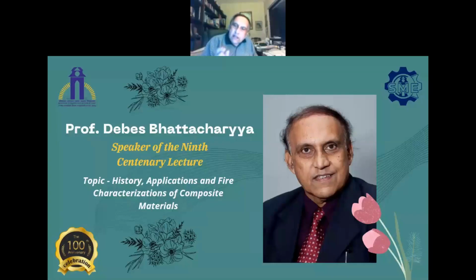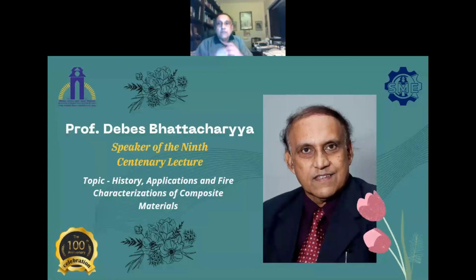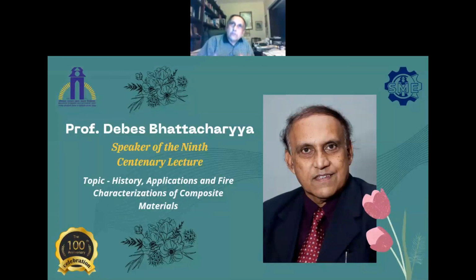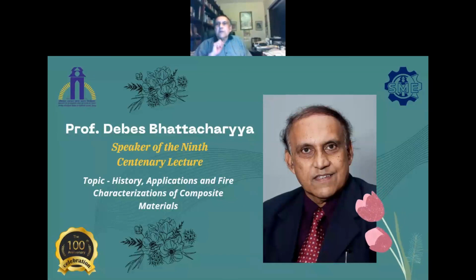We are trying to retain some fiber length so that we don't pulverize to a particle where the aspect ratio is almost 1. We are trying to keep some kind of aspect ratio, and add 2 or 3%, 2%, of nanomaterials like graphene or nano clay, which is quite cheap these days. Graphene is also very cheap. From Alibaba, you can get graphene quite cheap. That way you can arrest the mechanical property drop as well. So nano clay or graphene also helps in fire retardancy, but that property drop can also be arrested, because that is one bad aspect about all these fire retardants. They tend to drop the mechanical properties.